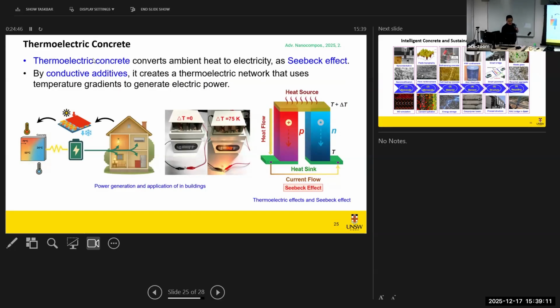Now, finally, I would like to talk about thermoelectric concrete. The thermoelectric concrete can convert ambient heat to electricity, and this is achieved by incorporating carbon nanomaterials and metal oxide. It can create a thermoelectric network, where temperature gradients induce ion and charge carrier movement inside the cementitious composite. And then because of this movement, we can generate electric power. This is the process called the Seebeck effect.